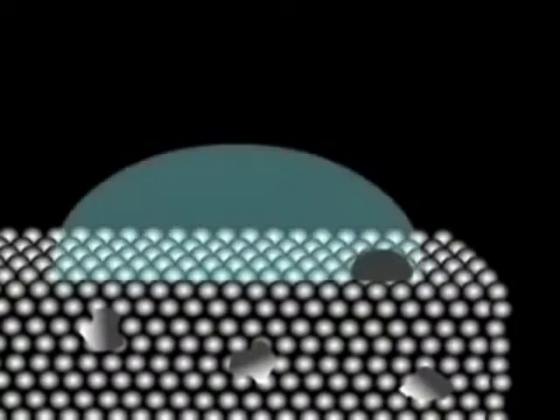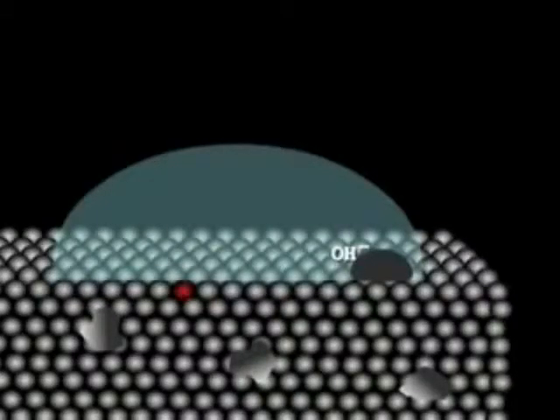Some of these will be exposed at the surface. If a lump is in contact with water, it will have contact not just with water molecules, but also dissolved salts and dissolved oxygen from the air. What we have here is a kind of natural galvanic cell. The carbon acts as an electrode because it provides a ready location for electron transfer. Here's what happens. When an oxygen molecule slams into the carbon, it grabs two electrons, which are dragged through the iron lattice from an iron atom.